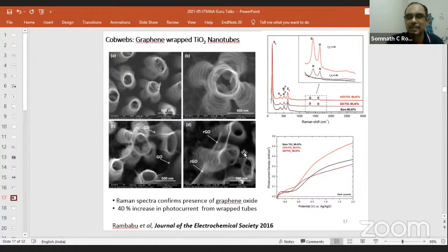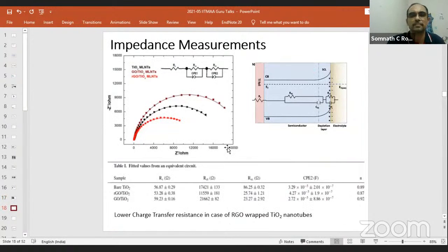I'm not going into the details of that. Of course, I can respond to queries later, even through email. And we found a substantial increase in the light harvesting and the current generating capabilities of this TiO2 nanotube with the help of this reduced graphene oxide. So mind it, I would like to say specifically that we are not calling these sheets or thin layers graphene, because they are not only carbon layers. They are carbon layers with some functional groups attached, which is called reduced graphene oxide. So this is one of the most beautiful works that we have been able to do.